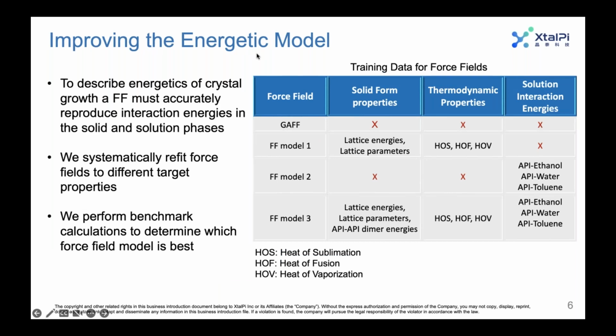The next thing that we use at XtalPi is tailor-making the force field. At XtalPi, we're very good at molecular dynamics simulations, and we have a lot of experience tailor-making force fields for specific pharmaceutical projects or other chemistry projects. What I'm giving you here is an example of the tailor-made force field process. For morphology prediction, in order to describe the energetics of crystal growth, a force field must accurately reproduce interaction energies in the solid phase and also the solution phase. So what we do is we systematically refit force fields to different target properties, and then we perform some benchmark calculations to determine which force field model best describes the system.